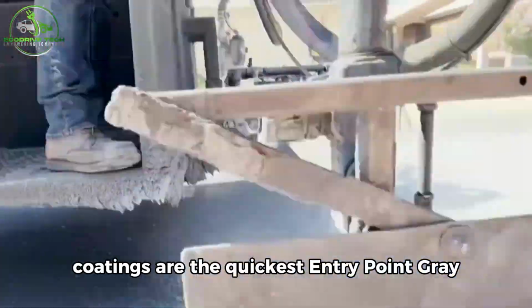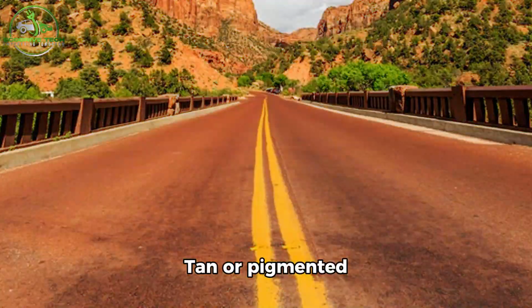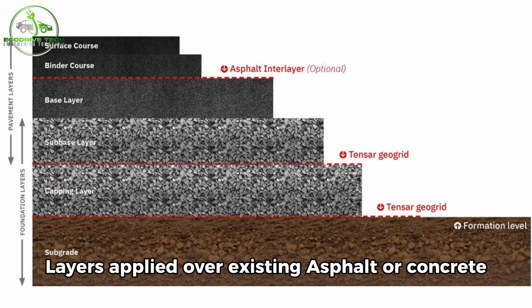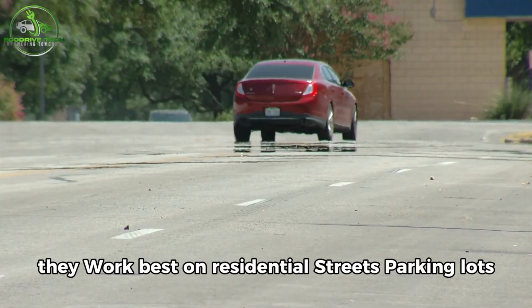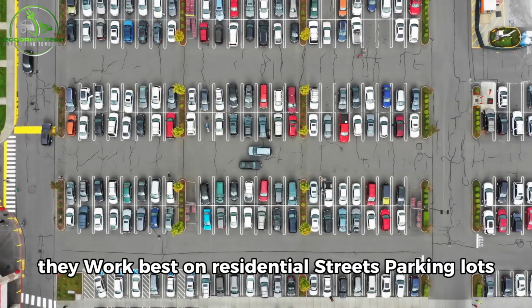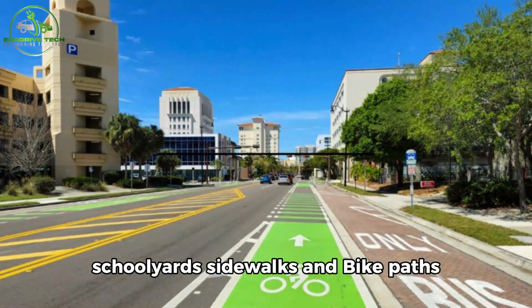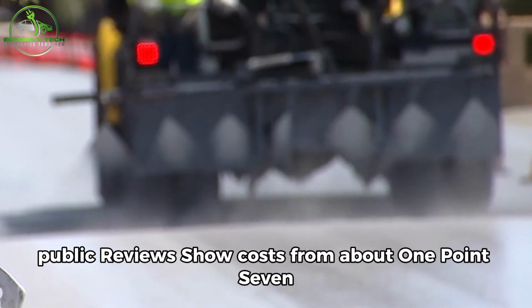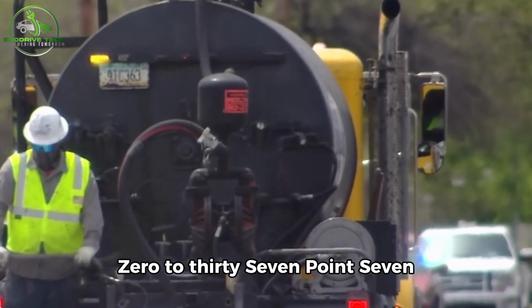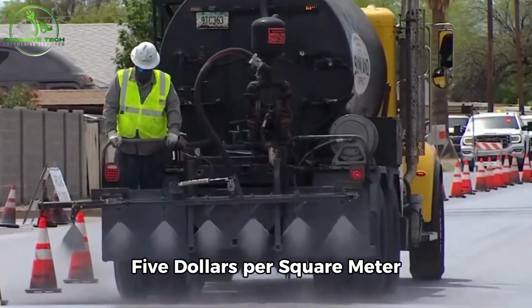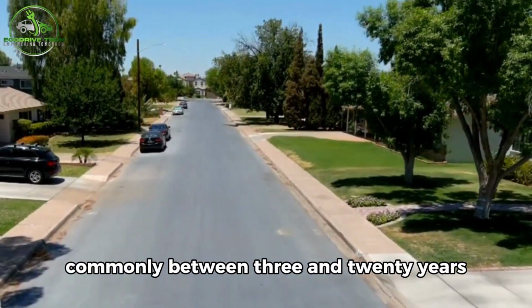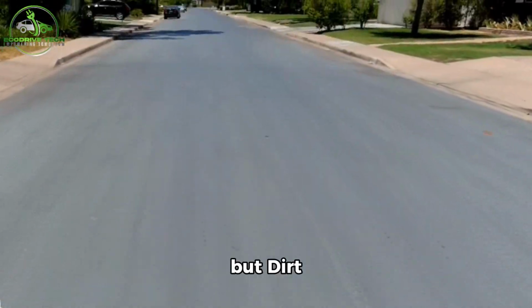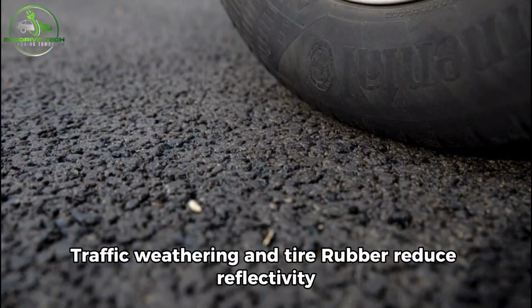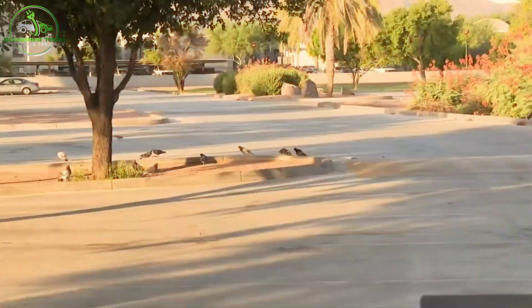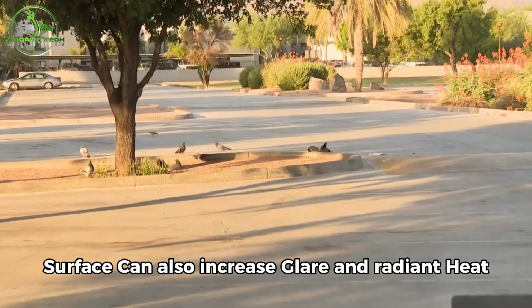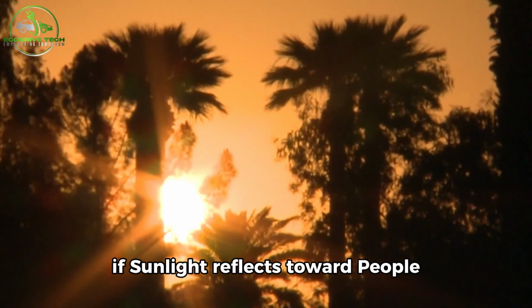Reflective pavement coatings are the quickest entry point: gray, tan, or pigmented layers applied over existing asphalt or concrete. They work best on residential streets, parking lots, schoolyards, sidewalks, and bike paths. Public reviews show costs from about $1.70 to $5.00 per square meter, with useful life commonly between 3 and 20 years. But dirt, traffic, weathering, and tire rubber reduce reflectivity. A cooler surface can also increase glare and radiant heat if sunlight reflects toward people.